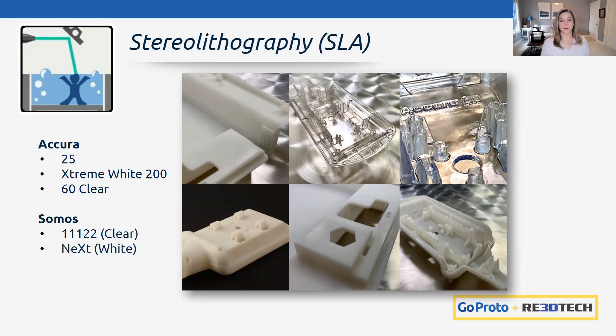A quick question: how do you prevent morphing of round or cylindrical features using SLA? That has a lot to do with build orientation. These are all layer-by-layer processes — they make round shapes in stair-step fashion. If you build a round feature in the Z, the laser will trace the outside and make it very round. If built on its side, you might get more of a stop sign shape. So orientation, intelligent supports during building, and post-processing treatment are important — as is careful shipping, especially during warm summer months when heat can affect parts.